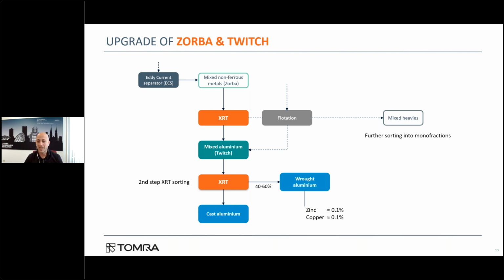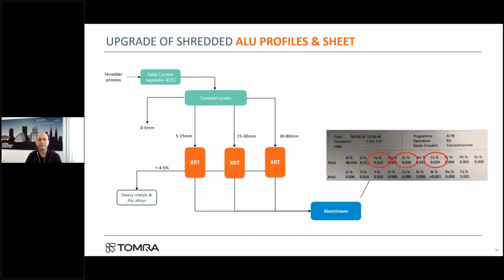And depending on the grain size and the input of the shredder, there can be about 40 to 60% of this wrought aluminum in a mix of typical Zorba. So this slide shows the process from one of our customers who are processing aluminum profiles and mixed aluminum sheet. This customer is operating a typical shredder process using a hammer mill, magnet, and eddy current separator.